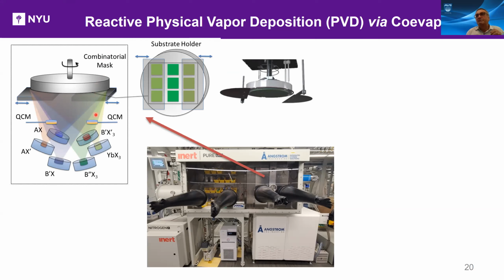We have a combinatorial mask that allows us to do high throughput synthesis. We typically work with 3x3 or 4x4 samples. So in a given deposition, we'll do 16 identical samples or 9 identical samples or 3 identical samples that may be annealed at different temperatures. We might put a gradient of composition and things like that. And our mask looks something like this. We have just started playing around with actually putting in continuous combinatorial gradients to make libraries of different compositions. We just started doing that.